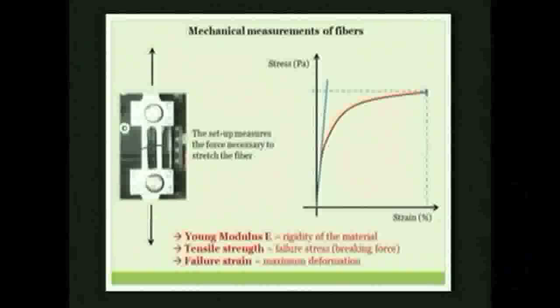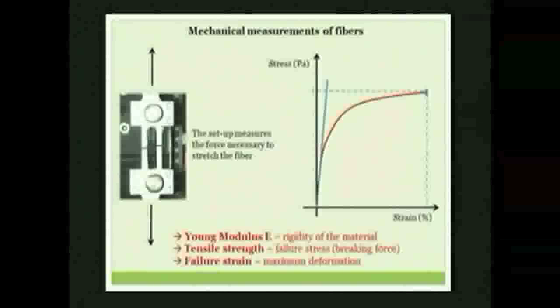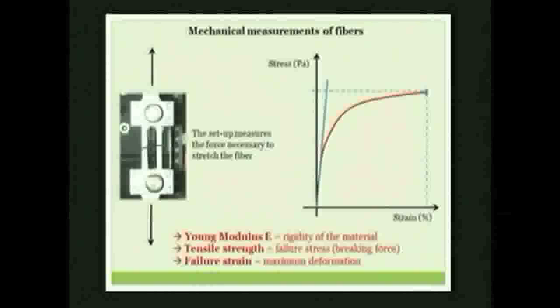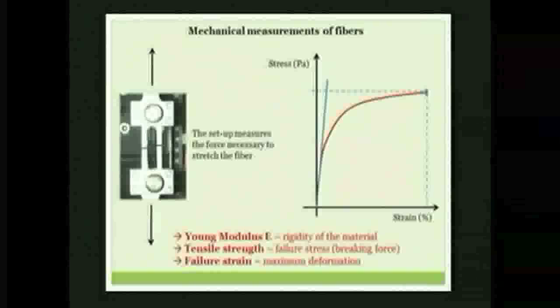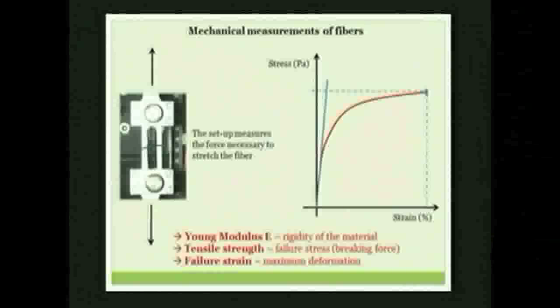And this is a typical stress-strain experiment. Here is the stress. The stress is the force that you need divided by the surface, the section of the fiber. Okay? Of course, the strain is the deformation rate. So, typically, this is the kind of curve that you will get. And so, you can extract different values from this curve. The first value that you can extract is the Young modulus, E, which defines the rigidity of the material. This is the slope of the first part of the curve, okay? This is the elastic regime, where the deformation that you apply is completely reversible.